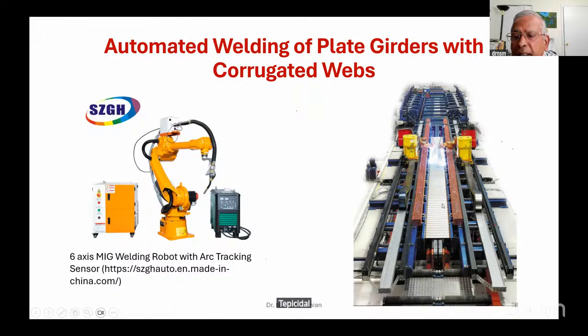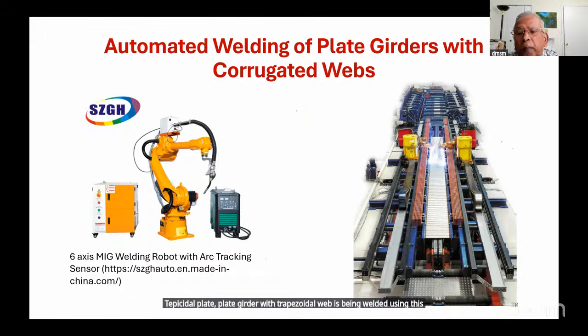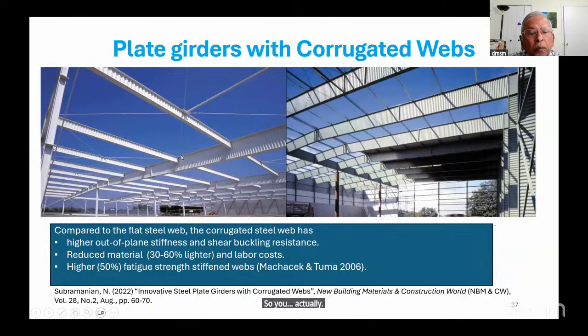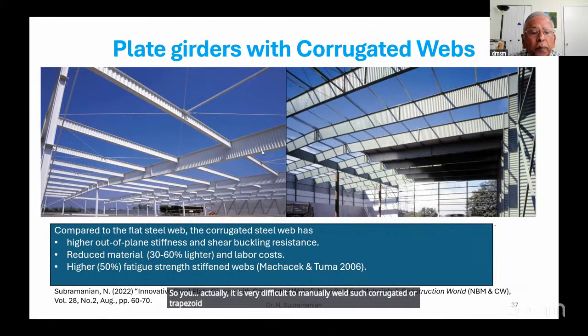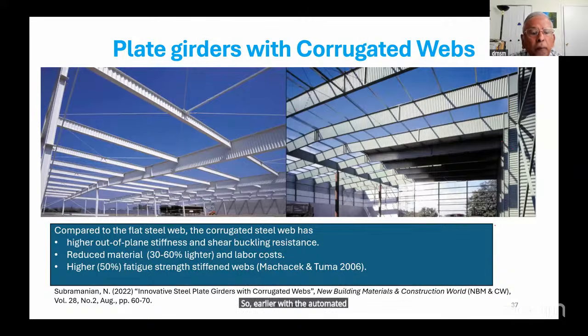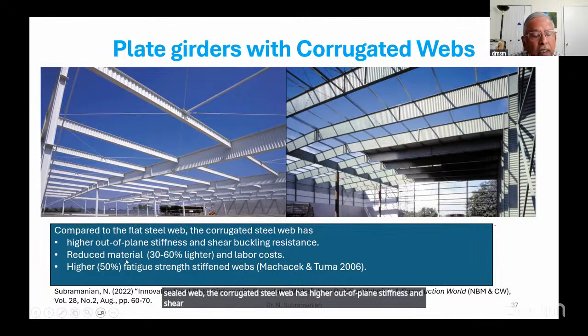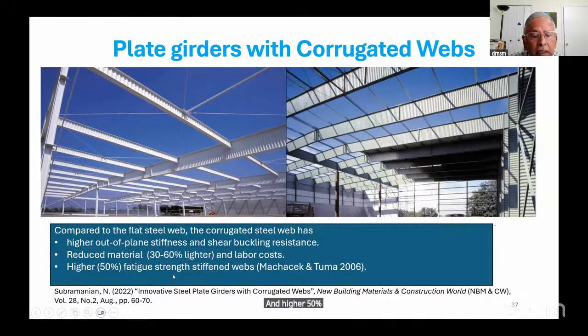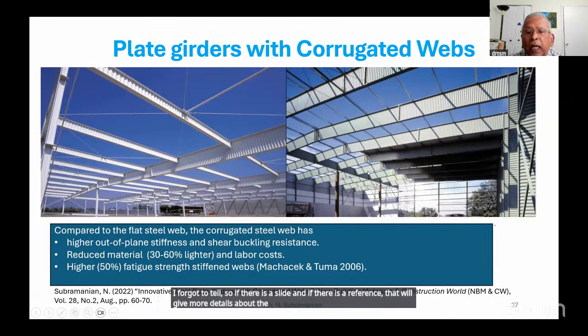trapezoidal plate girder with trapezoidal web is being welded using this automated welding system. It is very difficult to manually weld such corrugated or trapezoidal or any other shape of webs using manual welding. So only with automated welding it is possible. And compared to flat steel web, the corrugated steel web has higher out-of-plane stiffness and shear buckling resistance. It also has reduced material, 30 to 60% lighter, lower labor cost, and higher, 50%, fatigue strength because of the stiffened webs. I forgot to tell, if there is a slide and if there is a reference, that will give more details about the things I am discussing here.